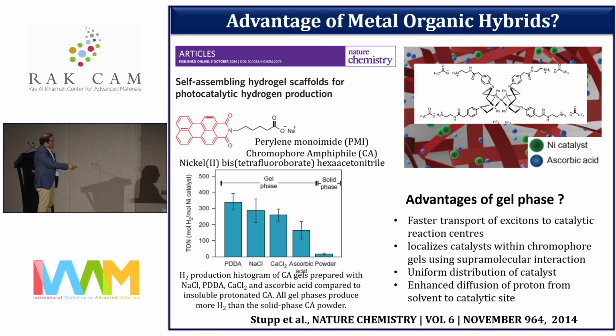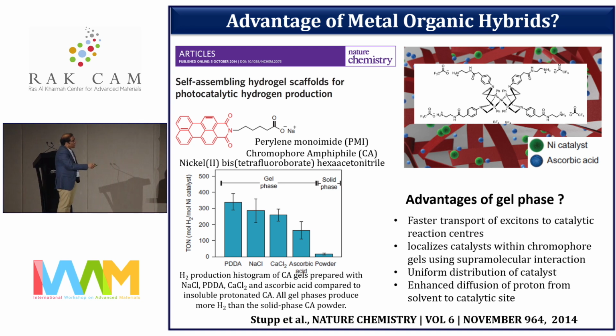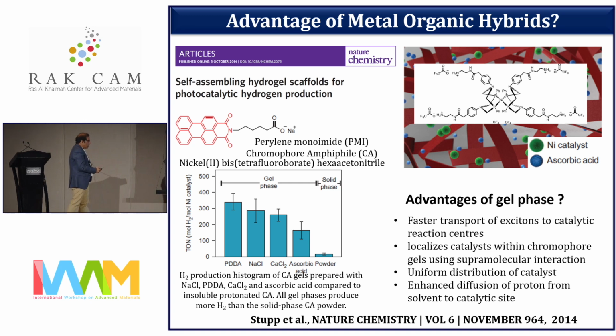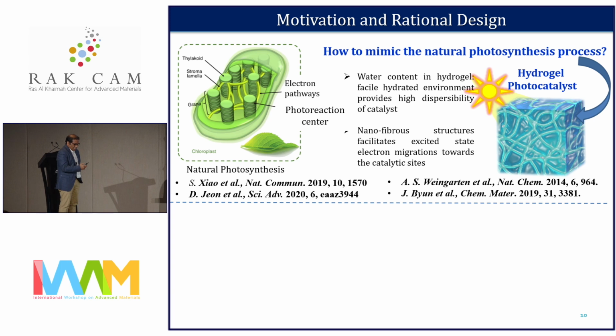But the one problem is that since they used the nickel complex as the catalyst, it is not covalently attached to the chromophore. So eventually, over a number of cycles, the catalytic activity slowly decreases because it comes out of the solvent system. To address this, we felt it should be covalently attached, and we can take help from nature.